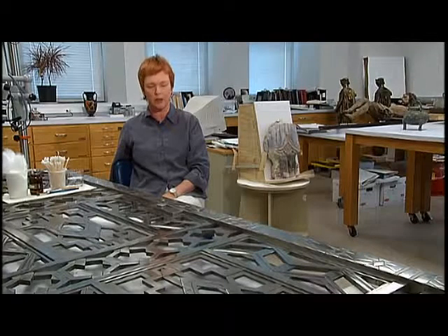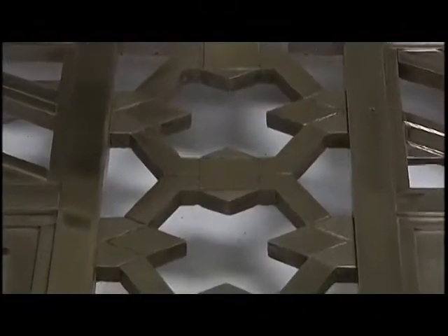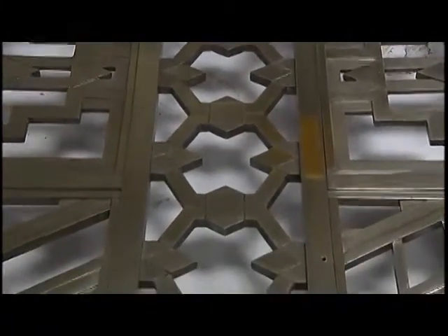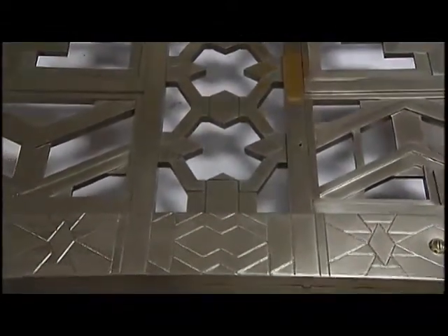One of the first things we do when something comes in and when we're going to treat it is find out what it's made out of. So in this case, we did some analysis work. We wanted to analyze the metal of which the door is made, and in this case, we used the X-ray fluorescence spectrometer. It was discovered that the 2 main ingredients were nickel, roughly 2/3, and copper, roughly 1/3, and some trace elements. And then in checking various reference books, we could determine that this, in fact, is a metal called Monel. And Monel was a precursor to stainless steel.